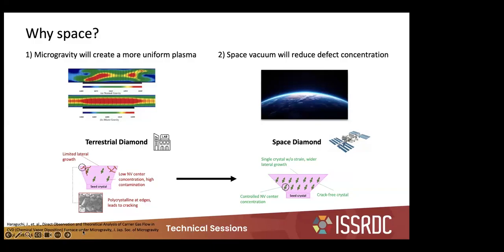There are two aspects of the space environment we're looking to take advantage of to grow higher quality diamond crystals. The first is microgravity. There's good indication from a small amount of prior work in the literature as well as simulation that the plasma in which the diamond is grown will be more uniform without buoyancy-driven convective flows. There's also space vacuum itself. High quality vacuum is very important in the production of semiconductor materials, and using space vacuum we hope will reduce the amount of nitrogen impurities in the final diamond.